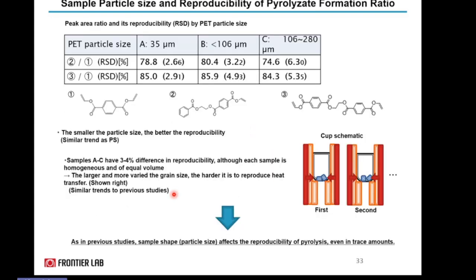So again, the peak area of these has been compared. We can see the best relative standard deviation, or reproducibility, is obtained for the smaller size compared to the larger size. So these two examples show the effect of grinding to make different samples into powder form and how it really contributes to data quality when you do chemical analysis. That is something we tried to demonstrate by analyzing two different types of polymer, polystyrene and PET, where we have shown better data quality when you have samples of smaller particle size.